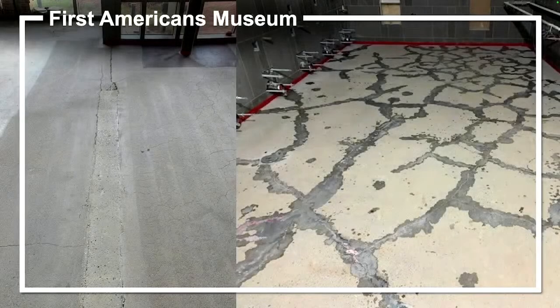And then this is the First Americans Museum in Oklahoma City. This one they wanted to have a decorative polished floor, but the floor needed tons of repairs. It had cracks, it had some deep spalls. So we used the Cementol for the cracks, and we even used the concrete mix for the deeper spall repairs. And they were able to come back and grind this after 1 hour because of the very high strength, and come back and put the True SP decorative polishable floor over the top of that, and the results turned out absolutely beautifully.